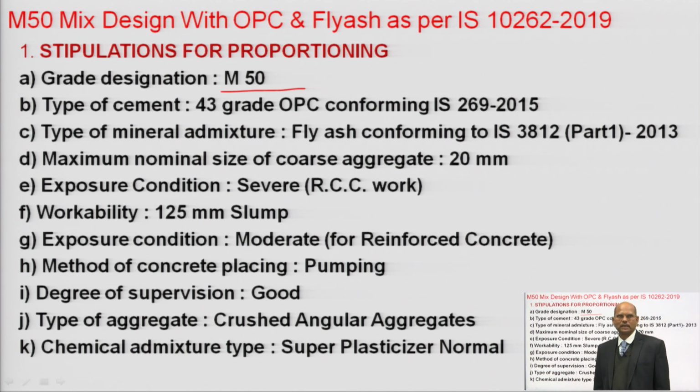The maximum nominal size of aggregate given is 20 mm, exposure condition is severe for RCC work, and workability is 125 mm for pumping.